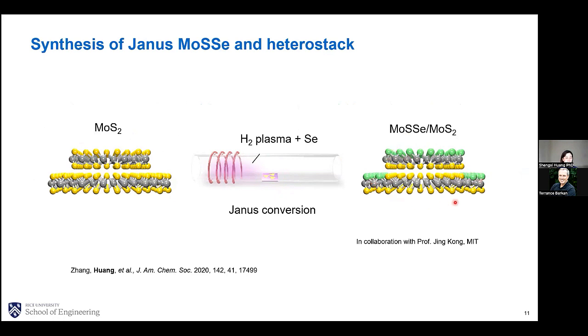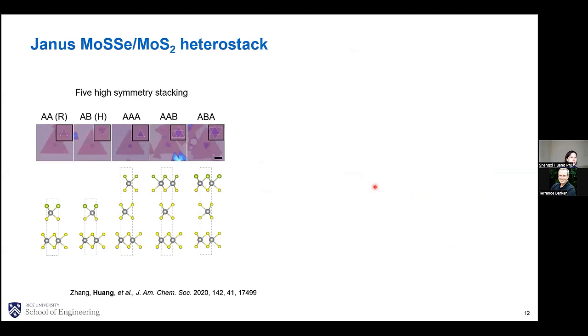So now in the center, you can see we have the Janus MoSSe and MoS2 heterostack. At the outer skirt, we have monolayer MoSSe. So in total, we obtained 5 types of high symmetry stacking, including AA and AB bilayers and several trilayers. For these heterostacks, the top layer is MoSSe, and all the bottom layers or the middle layers are